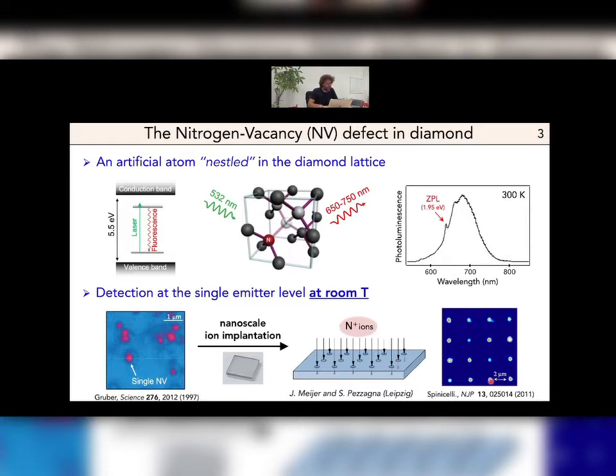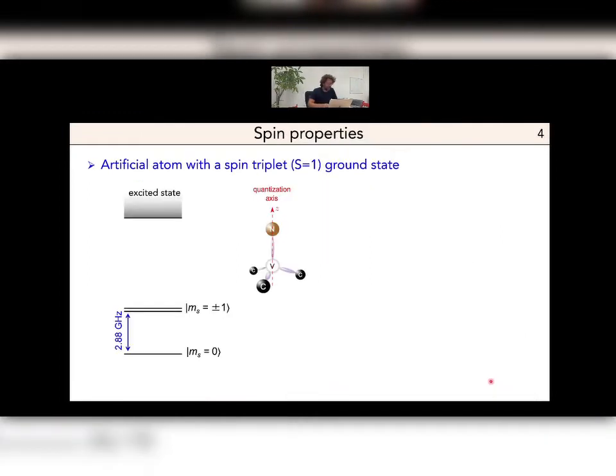The key property of the NV defect lies in its spin properties. The electron spin of the NV defect is a spin 1, and it exhibits a spin triplet ground state here, with a degeneracy between ms equals 0 and plus or minus 1 that is lifted by spin-spin interaction by an energy of something like 3 gigahertz.